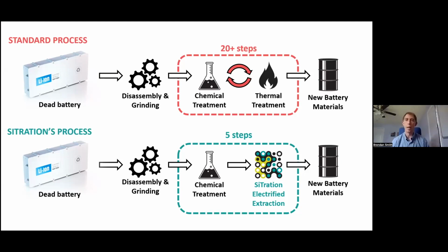So the standard process today is called either hydrometallurgical or pyrometallurgical recycling. What happens here is the batteries are either burned or ground up into a powder. This is called black mass powder in the case of hydromet. And then in both cases, that resulting material is dissolved into a harsh concentrated acid solution, which you see here. And from this point in the standard process, it undergoes about 20 to 25 steps where you're one by one extracting all of the impurities, all the contaminants from that stream until you're left with your new battery materials, namely lithium, cobalt, and nickel compounds. And those are really the 90%+ of the total value in these end-of-life battery materials.